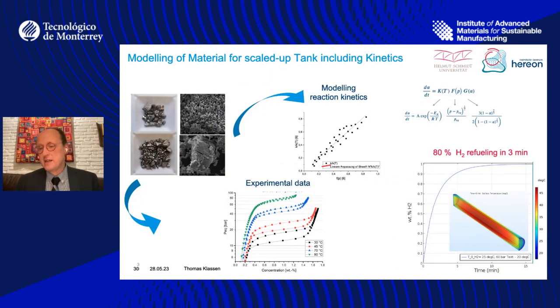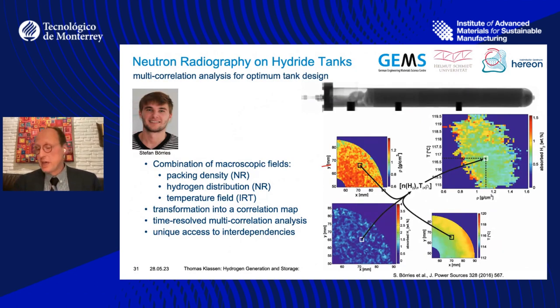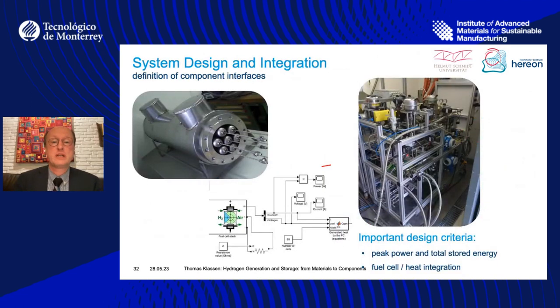So we then take all those data that we achieve on the material, transfer it to a metal hydride tank, and have a look at how the heat is distributed in the tank, the reaction heat, and how we can get it out again. And for that, we also have a cooperation with a nuclear reactor facility for neutron scattering, and we can see how the density of the material is, where the hydrogen goes, what kind of temperature development we have. And if we fold all of this together, we get to the sweet spot of how we should design our tank to be fast and efficient and store and release hydrogen.